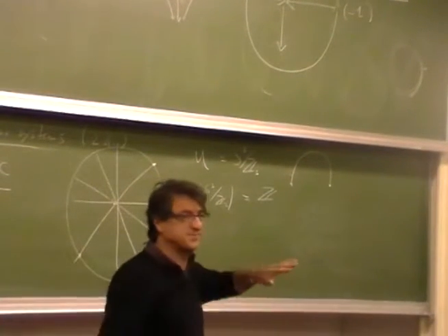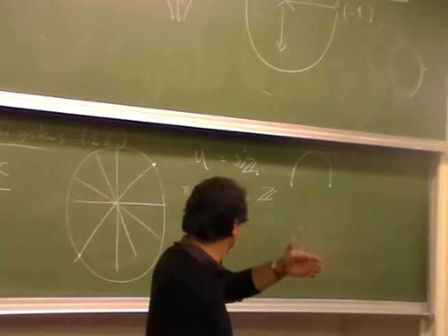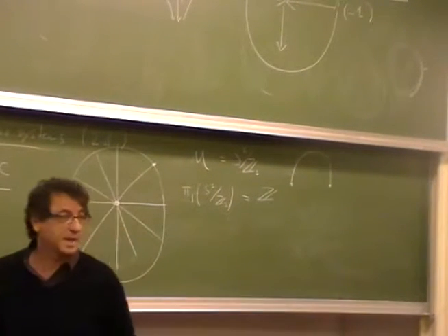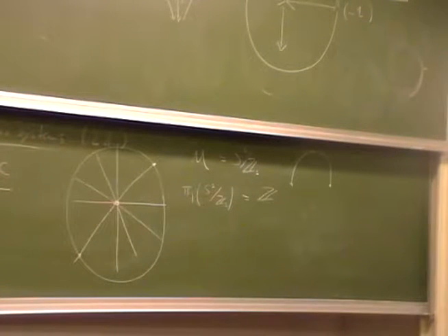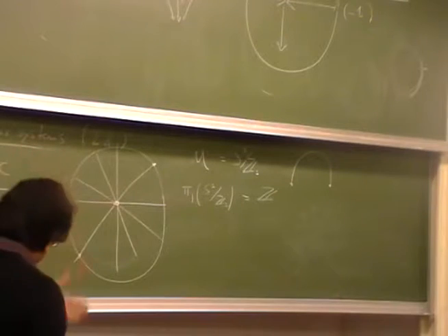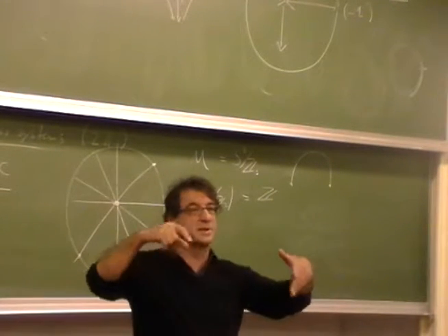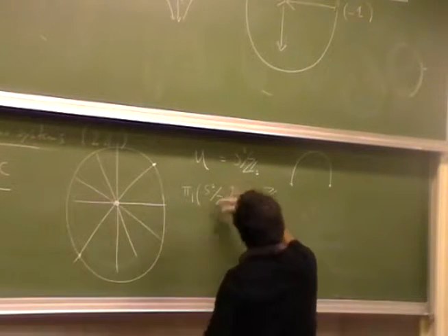This gives a pi 1 defect, but remember we're in two dimensions. So it gives a point, like a singularity. So it's a point defect. You can think of it as a cross section through the three-dimensional disclination loop we saw before. So you take a cross section through that, so you only have two spatial dimensions, we get a point. But we no longer have this route of escape into a third dimension and so on. So that changes the symmetry group of the defects.